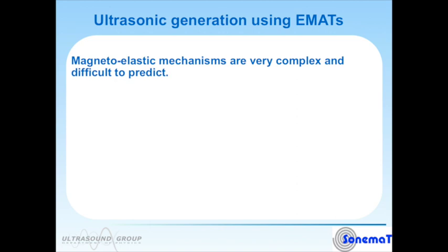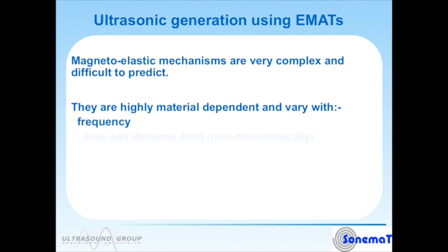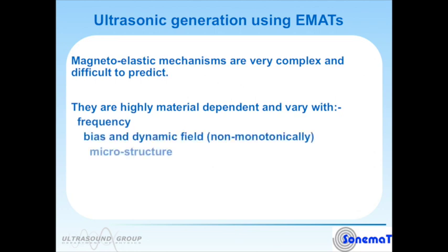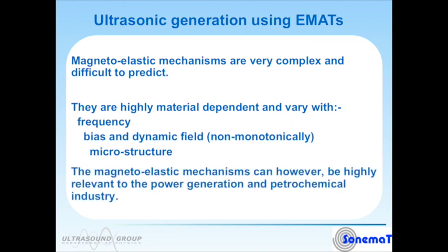Magnetoelastic mechanisms are very complex and difficult to predict. They are extremely dependent on material properties, and they vary with frequency, the bias magnetic field or the dynamic magnetic field that comes from a coil inside an EMAT, and the microstructure of the material. In many cases, the experimental data does not exist that would allow you to model the magnetoelastic mechanisms. These are the magnetic, magnetostrictive mechanisms. Generally, the best way to find out how an EMAT will perform is actually just to place it on a sample and see what happens.